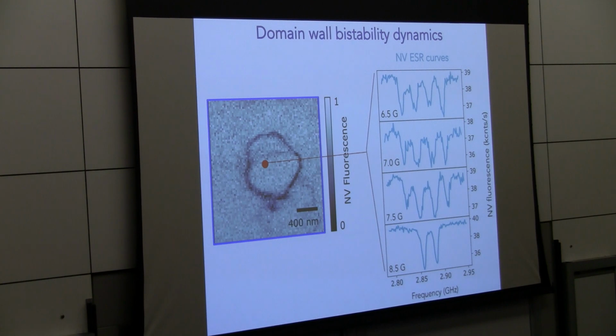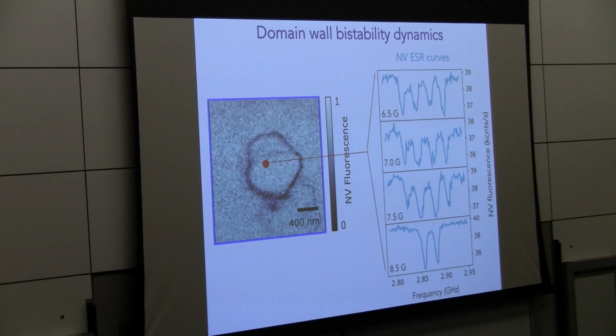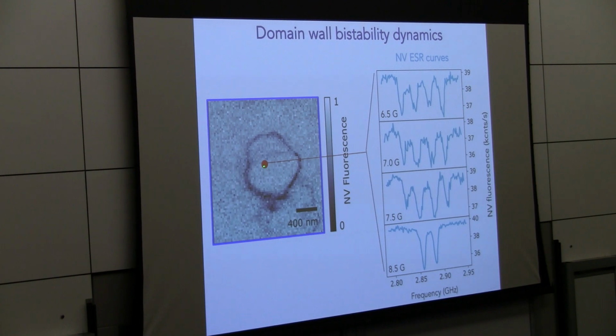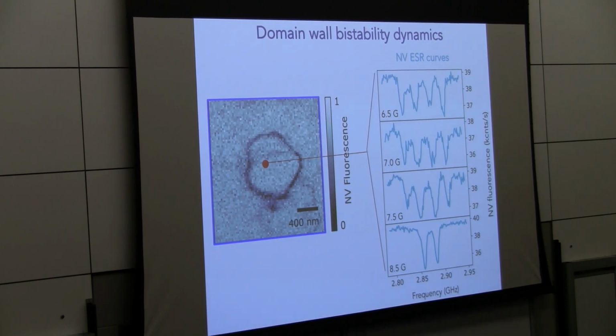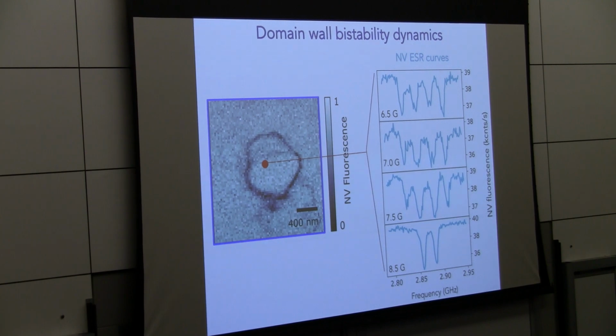What's happening is this domain wall is actually jumping in real time between these two stable positions, presumably between two pinning sites. We can see that by fixing our NV center in one location and taking one of these ESR, or ODMR, optically detected magnetic resonance curves, where you would naively expect to see just two peaks corresponding to one magnetic field splitting. But because the domain wall is spending some time in one spot and some time in another spot, we actually see two different fields during the time scale of the measurement, and so we see two discrete splittings.